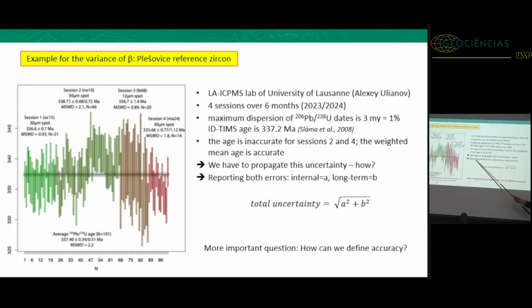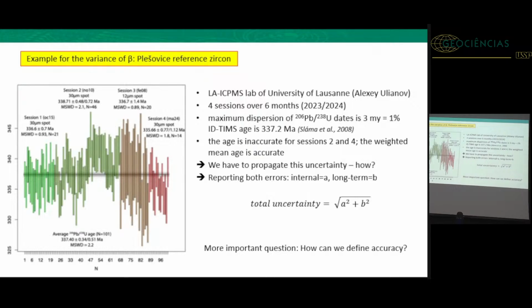So we have to somehow propagate this fact onto our unknown age. But how? So we can do the simple way. So we take the uncertainty A, which is the uncertainty derived from data scatter from your laser, from your sample. The beta would be the data scatter of your secondary standard, which is actually not so bad. We are in the per mil range. So we do not really increase the uncertainty so much by this. But the more important question is the accuracy. So here we are ending up with an uncertainty still of plus minus 0.3%, but we know that actually our dispersion, our inaccuracy could be 1% or even more. So how would we do this?